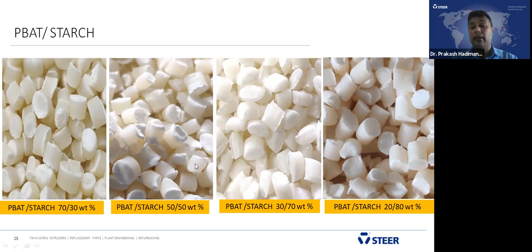Up to 50-50%, we were able to make the blown film and get better elongational flow. And at 70% and 80% starch, because of the viscosity, we could not make a blown film, but these two blends can be utilized for injection molding. Finally, we went for sheet line and injection molding, where you have spoons and all. Those things can be utilized for other applications. Where you want to make carry bags and all, 50-50 is a good amount. And we'll try to make it 65 so as to get better results in the blown film.